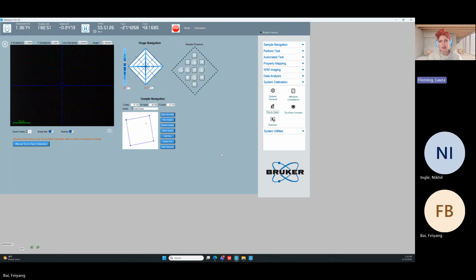Right, so in the equations, hardness is the maximum force divided by the contact area. Reduced modulus is the stiffness divided by the contact area, or the square root of it. Contact area. Do we remember what contact area is? So contact area is how much of the probe is in contact with the sample at the time of the indent, correct? Yes. So the tip area function gives us the relationship between contact depth and contact area.